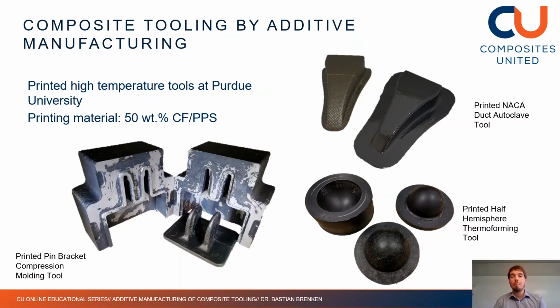and you also can see a part that was created with this tool in the autoclave. So using high temperature materials, like for instance the material used here, the PPS material reinforced with 50% carbon fibers by weight, you can definitely print high temperature tools like autoclave tools. And then at Purdue we wanted to see how far can you actually take it, and we tried to print tools for different high temperature applications.